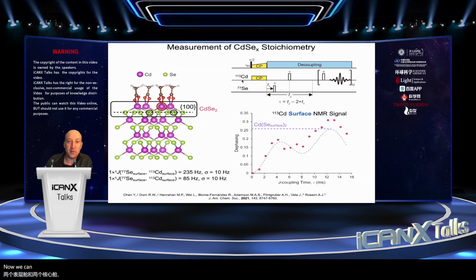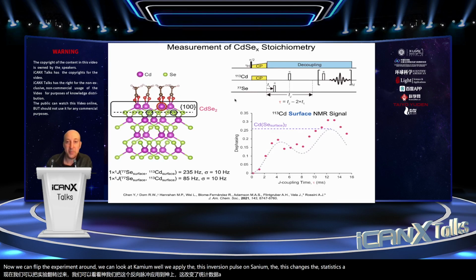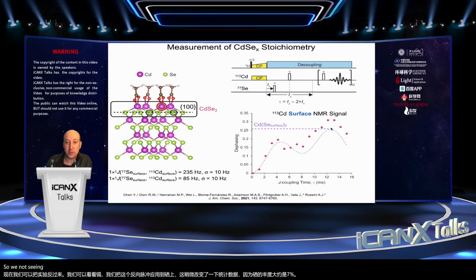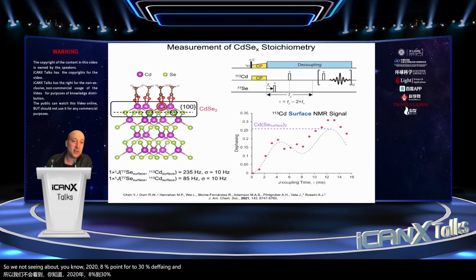Now we can flip the experiment around. We can look at cadmium while we apply this inversion pulse on selenium. This changes the statistics a bit because selenium is about 7% abundant. So we end up seeing about 28% or 30% dephasing. And so this is really consistent with those surface cadmium atoms having bonds to 2 seleniums.